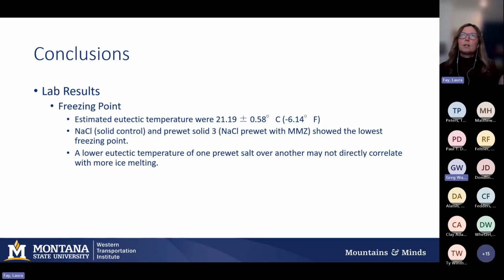What was also interesting when you compare these results to the ice melting is that a lower eutectic temperature for one pre-wet salt over another does not directly correlate to more ice melting.